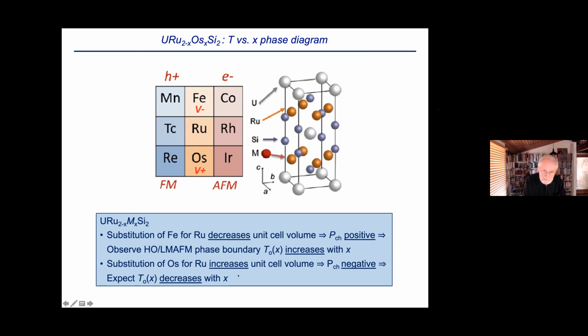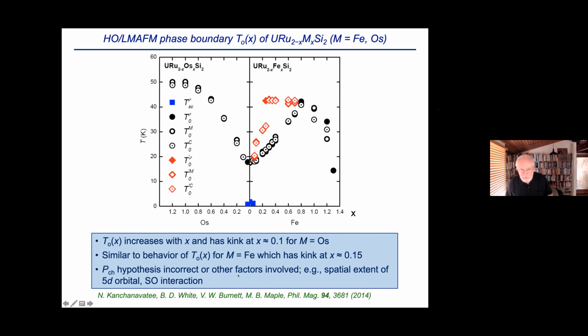And when we did the osmium substitutions later, these are polycrystalline data. So this is for iron substitution. These are small features that you see for the polycrystalline samples, and they're just spurious features, and you can disregard them. These are the actual phase transitions, which we measured in detail, just like the data I showed you for the single crystals. So the real phase transitions occur along this region for iron.